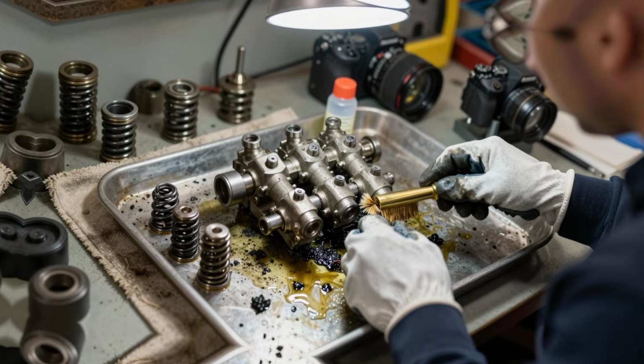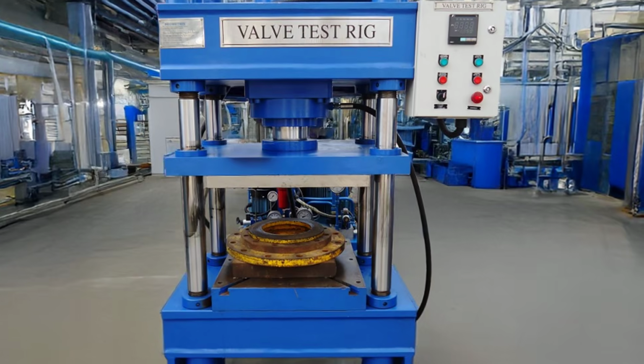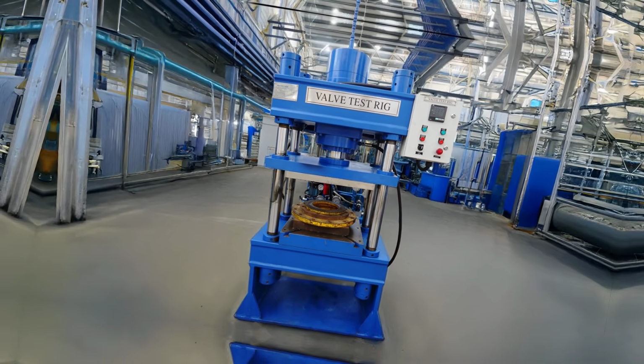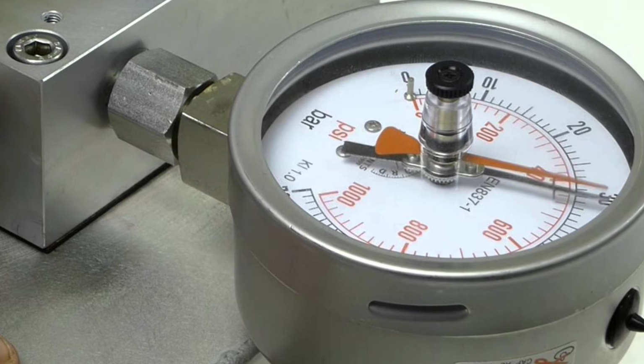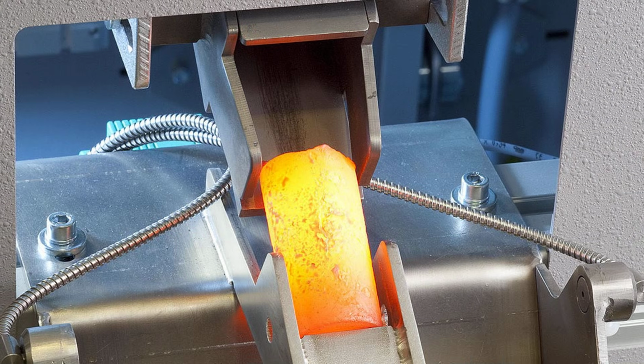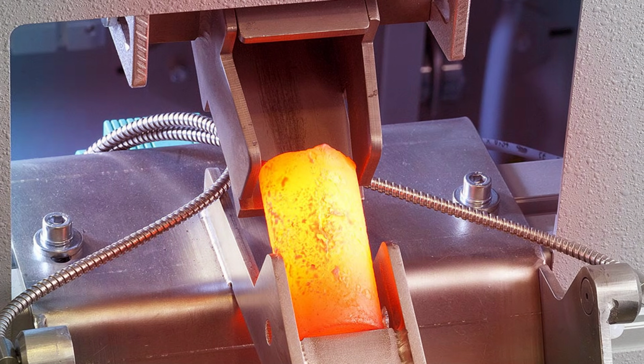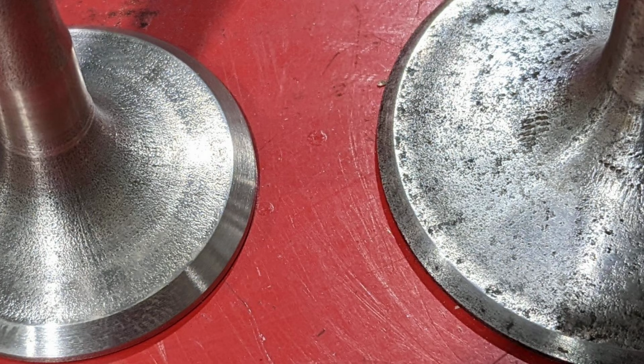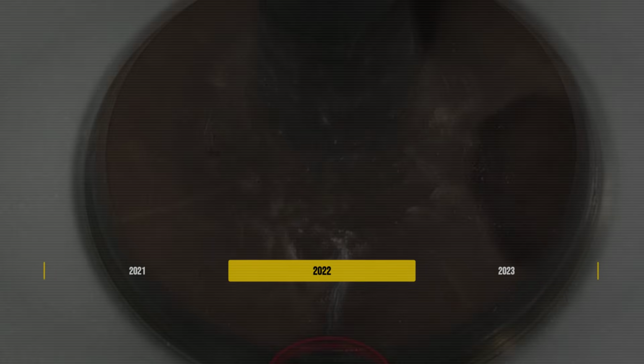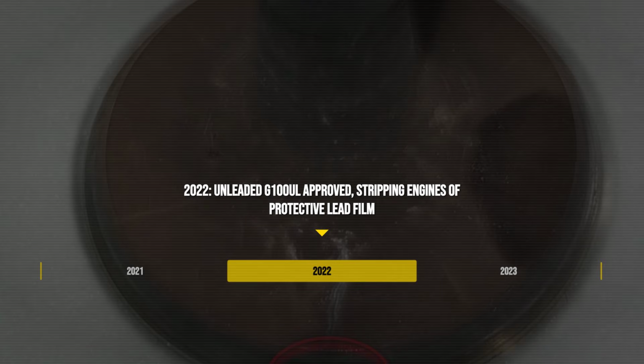It strips away the old deposits, leaving only bare steel and iron to fend for themselves. Every time the engine fires, those surfaces are hammered together at hundreds of pounds per square inch. At 700, 800, even 900 degrees Celsius, the metal softens just enough for the peaks to weld, then shear, then pit. The result is a contact band that goes from mirror smooth to cratered in less than a season.